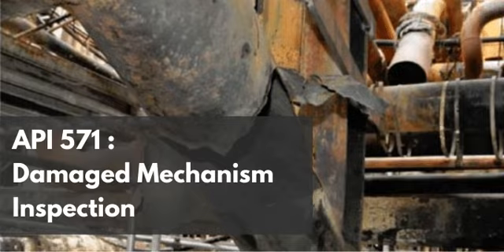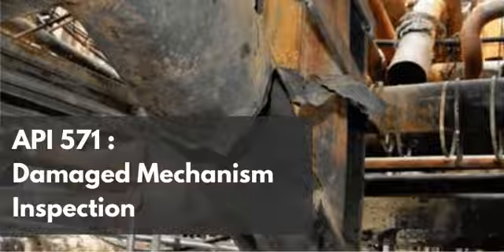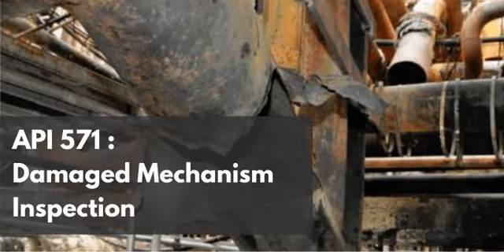So the absence of post-weld heat treatment is what transforms a standard piece of industrial carbon steel into a highly susceptible target. Absolutely. As we established, stress corrosion cracking is a synergistic mechanism. It requires three concurrent factors: susceptible material, aggressive environment, and high tensile stress. You got it. The carbon steel provides the susceptible grain boundaries. The amine provides the environment. But it's the lack of PWHT that provides the critical threshold of tensile stress.